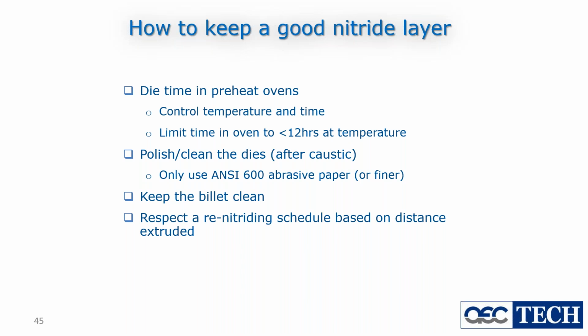So from an extruder's point of view, which most of you out there are, I believe, here are the things you control. You send the die off for nitriding, either internally in your die shop or externally for someone to nitride it. And we have to have some faith that that equipment is good equipment and it's properly run by a computer. But when the die is in the plant and it's been put in a die oven and forgotten, or something's happened, the press has broken down but we didn't cool the die ovens down, the die spends more than 12 hours in there at temperature, you're beginning to damage your nitriding.